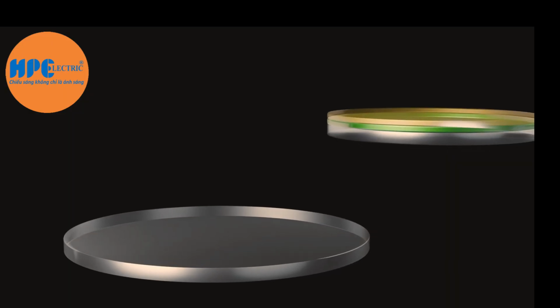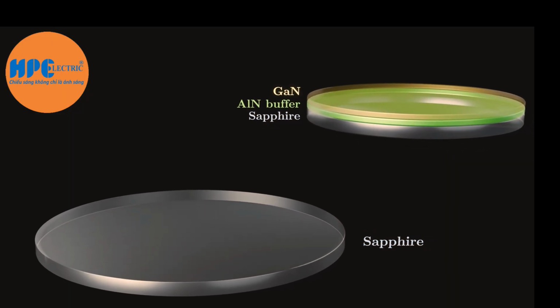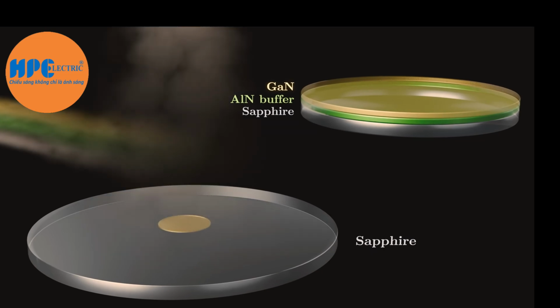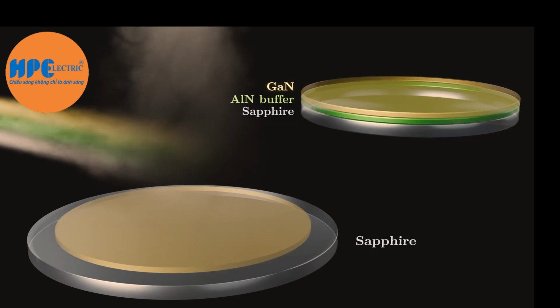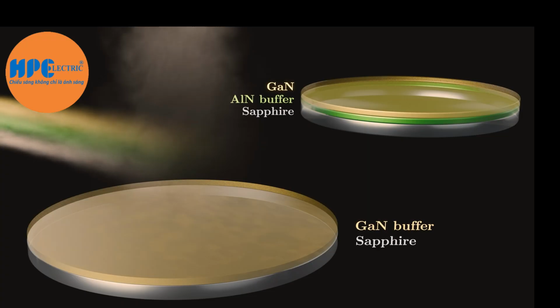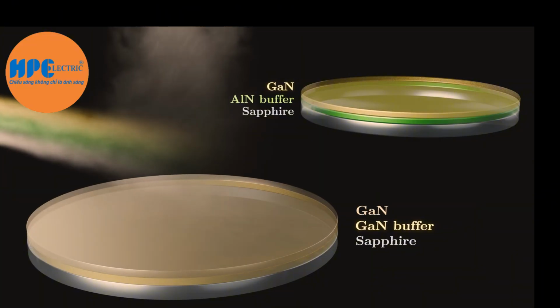Now he was ready to take on Akasaki and Amano. But instead of copying their aluminum nitride buffer layer, his two-flow design allowed him to make gallium nitride so smooth and stable, it itself could be used as a buffer layer on the sapphire substrate. This, in turn, yielded an even cleaner crystal of gallium nitride on top, without the issues of aluminum. Nakamura now had the highest quality gallium nitride crystals ever made.